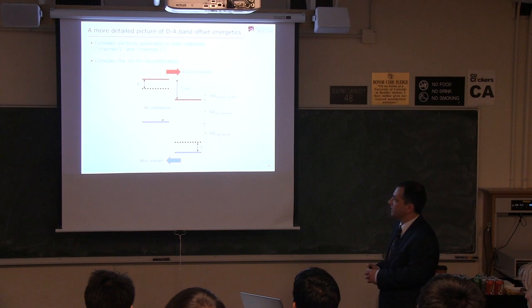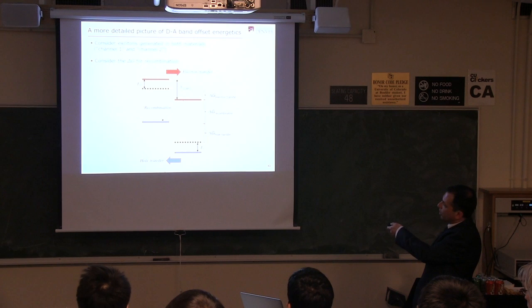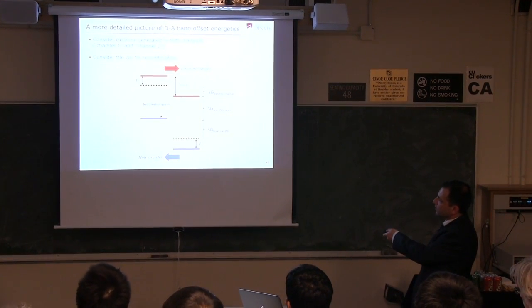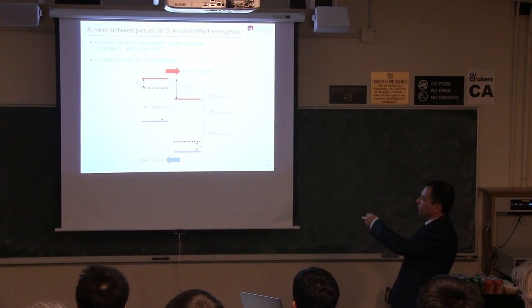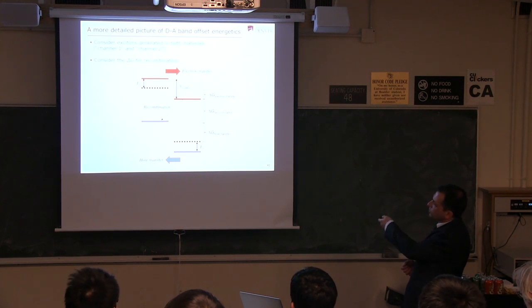One is the Gibbs energy of the electron transfer event, which is delta LUMO minus this thing called exciton binding energy. That's the Coulombic attraction between electron and hole. There's also a delta G on the other side of the device, because we can absorb into the acceptor and transfer a hole back to the donor, just as we can absorb into the donor and transfer an electron to the acceptor. So we have these 2 pathways. And finally, there's a delta G associated with the recombination. If we have an electron here and a hole here, there's a recombination, and we gain delta G in that system.